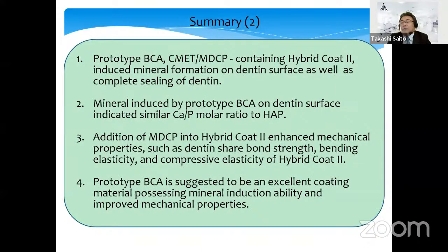As summary 2, the prototype BCA, which is a CMET and MDCP containing Hybrid Coat 2, induced mineral formation on the dentin surface as well as complete sealing of dentin. The mineral induced by prototype BCA on the dentin surface indicates a similar Ca/P molar ratio to HAP. The prototype BCA is suggested to be an excellent coating material possessing mineral induction ability and improved mechanical properties.